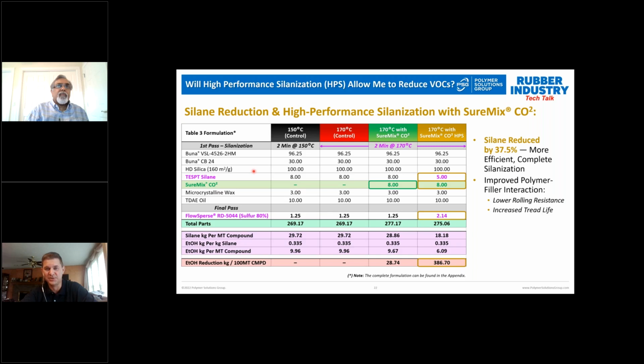So if you're familiar with the processing of Si69 in silica treads, 170 degrees C is something you would typically not do because the processing is not going to be so great, because you get liberation of sulfur and you get cross-linking in the mixer, and your processing goes bad quickly. So we also have a compound at 170 degrees C silanization temperature using SureMix CO squared. And then the final one here is 170 degrees C silanization with SureMix CO squared, but with a reduction of the silane by 37%, 38% in fact.